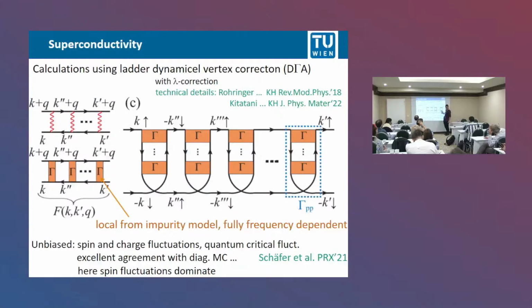Yeah, indirectly it might be possible, but what we do is we take the spin fluctuation, we go to the particle-particle channel, but we don't put the particle-particle fluctuations back. And because of that, we get a mean field kind of description for the superconducting TC and not a Kosterlitz-Thouless transition. Whether if you do it self-consistently, you get a Kosterlitz-Thouless transition needs to be seen. Because of that, we get this mean field and not Kosterlitz-Thouless transition.